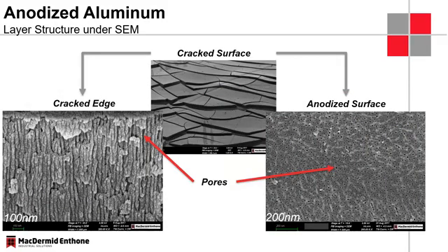When we look at an anodized surface and we want to do a cross section, it's not easy to do these cross sections, because by polishing the sides of the anodized layer we will actually polish over these little pores and channels that run all the way from the top to the substrate. So what we do is we crack the surface, and then we have a look at the side elevation of this surface, and that's what we see here on the left. So the picture on the very left is the side elevation, and what we see here is these channels, the pores you see from the surface. They run all the way down these anodized layers to the substrate, and these channels are really what gives the electric conductivity for any further anodizing and building an even thicker anodized layer.